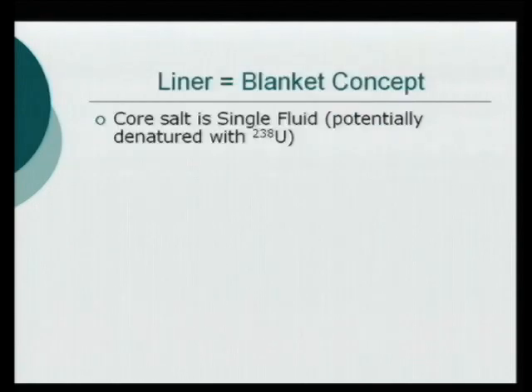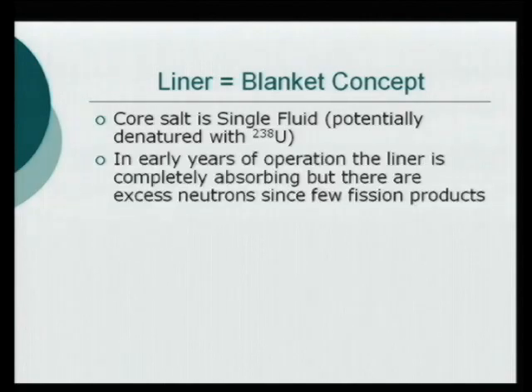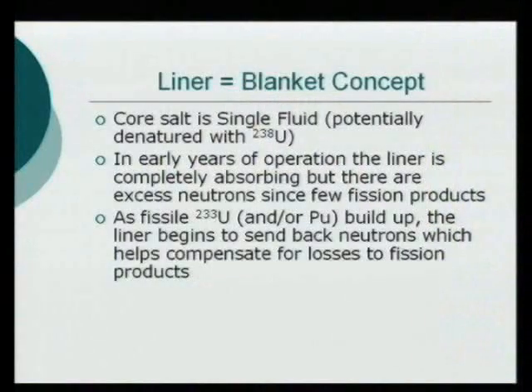But in that design, what I sort of call a liner equal to blanket, the core salt is a single fluid, potentially denatured with U-238, especially in the harder spectrum. U-238 doesn't hurt you as much. So in the early years of operation, the liner is almost completely absorbing. That means you're losing neutrons, but we don't have very many fission products yet, so the neutron budget should still be fine. Now, as fissile U-233 and/or plutonium start to build up in that blanket, it's going to start making more fissions there, which will increase the power a bit, and also start reflecting back more neutrons, which is what we need because we're having more fission products to absorb neutrons in the salt.